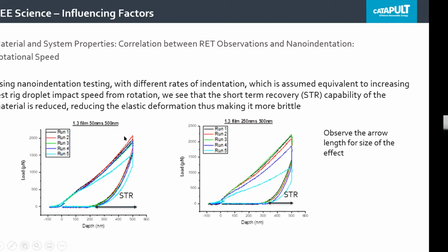So in this first case, we had a look at rotational speed, where we looked at using two different rates of nano indentation. So 50 nanometers per second, and then 250 nanometers per second on the right. If you observe the length of the arrow, to consider that as the size of the effect, the short-term recovery at the higher indentation speed actually reduces the amount of elastic deformation.